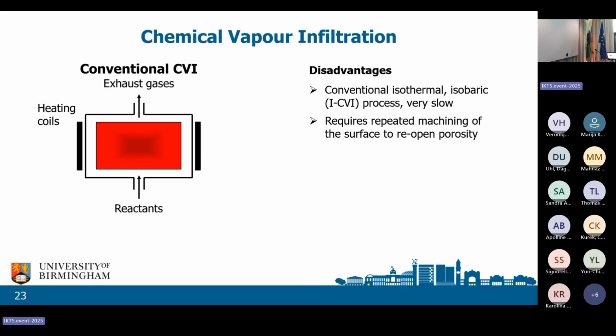So the outside is where you deposit first, you partly fill it, you get a crust on the outside, you've stopped your channels being open. Now you can no longer get the gases through. The gases are just going around the part. So you stop the process, take the parts out, machine them, put them back in, and start it again, heating it at 1 degree per minute up to 1,000 degrees. Very, very slow. And you need to do that 2, possibly 3 times. 1,000 hours to make each aircraft brake.